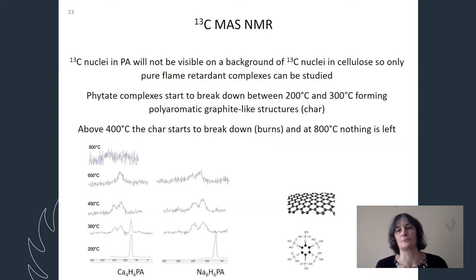So we look at the atoms in the sample, carbon atoms, and later I will show phosphorus atoms. And we have reference compounds with a certain electronic distribution around the carbon and phosphorus atoms. When something happens with the samples, the electronic environment changes, and then the peaks that we detect with radio frequency radiation will shift compared to the reference. So the scale on those spectra is in ppm, parts per million shift from the reference compound. So this is what we see when we look at the carbon atoms in the phytic acid.